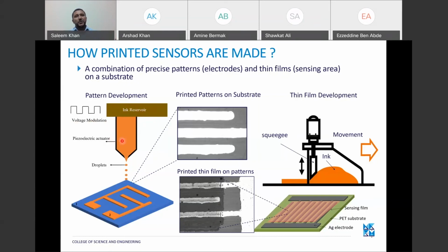So with each pulse actuation, it ejects a droplet. And these droplets are tuned in such a way that their frequency and their droplet size are set so that the final devices or the final structures that we achieve on a substrate are continuous lines or a uniform layer. Here in this case, you can see that droplets are ejected at a specific frequency.